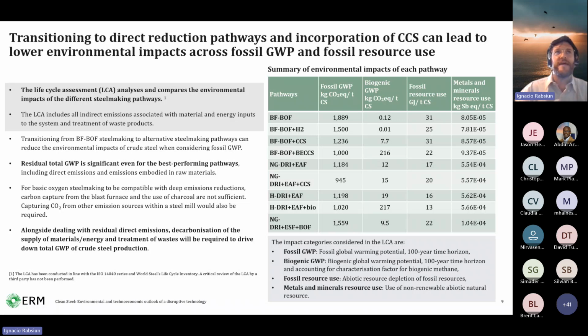After completing that analysis, we did a full LCA modeling of each of these 9 pathways. In this full LCA modeling, we considered not just Scope 1 and Scope 2 emissions, but also the emissions associated with all material and energy inputs to the system. We consider the fossil global warming potential, as well as the biogenic global warming potential, and other LCA impact categories like fossil resource use and metals and minerals resource use, where we found that for basic oxygen steelmaking to be compatible with deep emissions reduction, as you can see in the third row in this table, capturing CO2 just from your blast furnace, even if it has a top gas recycling modification, won't be enough to deliver deep emissions reduction. So addressing emission sources from other point source emissions in your steel mill, like the sinter plant, the coke plant, or the lime kiln, will also be necessary.